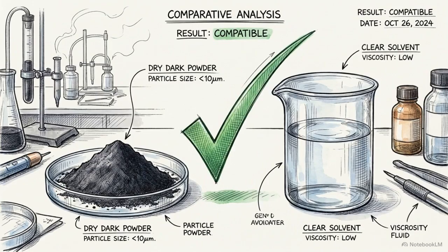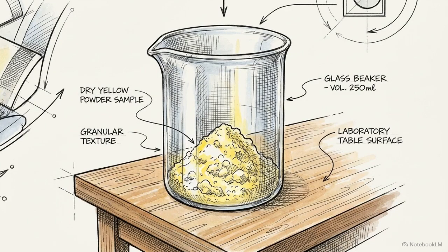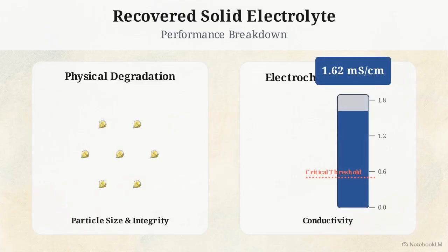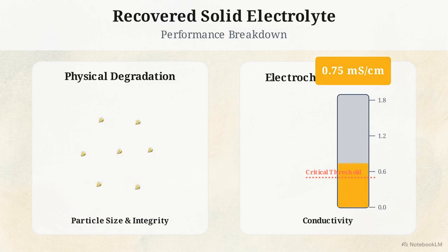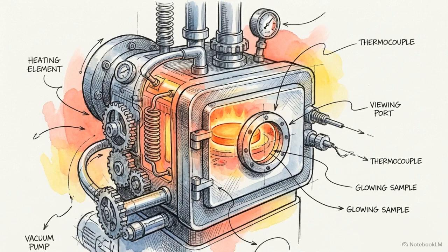By exploiting the distinct solubility of the inorganic solid electrolyte, we harvest the core components in their original forms without using any toxic acid. Once the ethanol is evaporated, the recovered solid electrolyte is safe, but it suffers a severe electrochemical penalty. The dissolution process reduces its particle size, and its ionic conductivity drops sharply to just 0.75 millisiemens per centimeter. That degradation, however, is entirely reversible once it undergoes targeted thermal annealing.